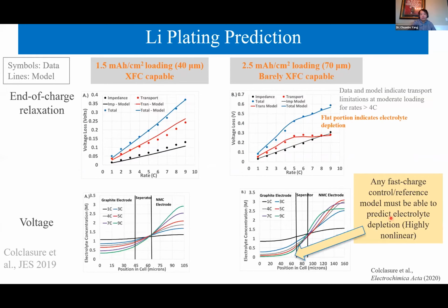To further investigate the nature of the difference in charging behavior between the low and moderate loading cell, the overall potential at the end of the constant current charging was characterized by current interruption voltage relaxation. This analysis is focused on distinguishing between overall potential associated with almost instantaneous phenomena, i.e., impedance, and that with a characteristic time related to transport. While plating occurred, the moderate loading cell exhibited a transport overpotential plateauing at rates above 4C, indicating the high rate charging acceptance is severely limited by the transport losses. The electrochemical model fits the measured overpotential well and is used to investigate the cause of the severe transport limitation measured for the moderate loading cell at high charging rate.